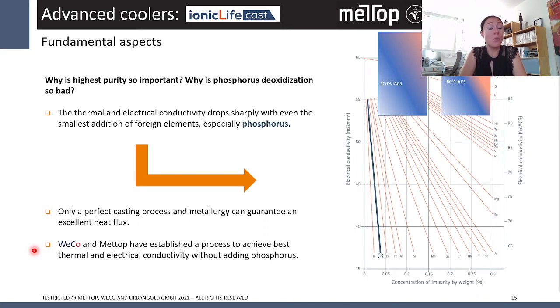Why is this so important? Why is high purity so important? Whenever you think of any impurities in the copper at all, you decrease your electrical conductivity tremendously. So if you really have only copper, you can go up to 100% IACS, and this is only possible with this special casting process.